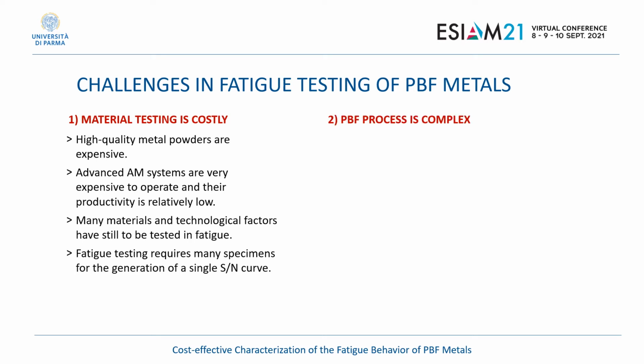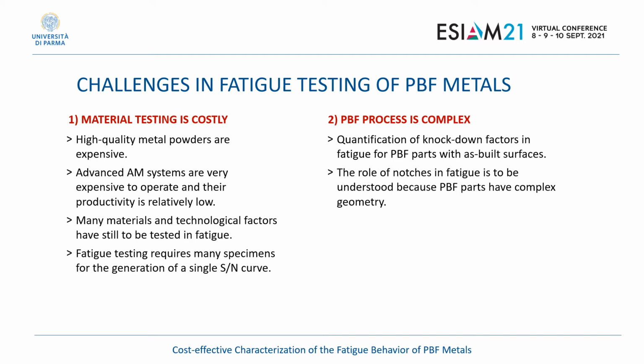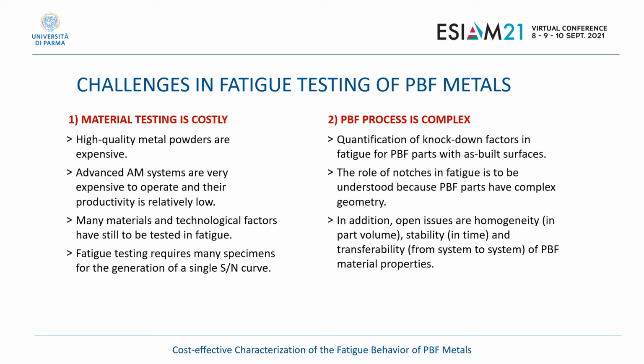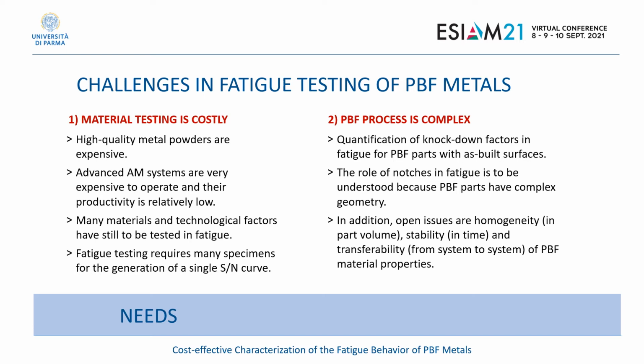In addition to this challenge, there is another one, related to the complexity of the PBF process. We have seen that we have to deal with parts that could have surfaces in the as-built condition. So we need to determine knockdown factors specific in fatigue for determining the lifetime of those objects. We saw geometrical complexities like notches and reentrant corners, which we know are important for the fatigue strength of the part, and so we need to determine also the influence of those features on the fatigue behavior. And finally, there are also still open issues like homogeneity, stability or transferability of the material properties that are thus determined.